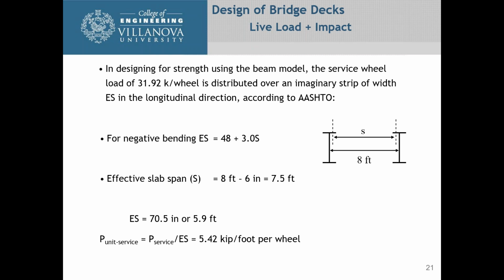Now, that is how much load the wheel applies. But AASHTO allows us to distribute that wheel load in the longitudinal direction a certain distance, which is called E sub S, the equivalent slab. For negative bending, which is the case we're looking at, E sub S is equal to 48 plus 3 times S, and S is the effective slab span. In our case, we're 8 feet center to center of girders, and then it's at the quarter points of the flanges, and our flanges are 12 inches wide. So therefore, our effective slab span is 7.5 feet. When you put that into the equation, you end up with E sub S of 5.9 feet.